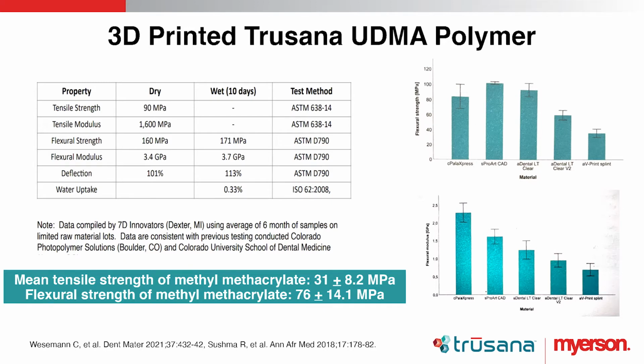When you compare Trusana, as far as the flexural strength and also the modulus, to, say, methyl methacrylate, the flexural strength is double, okay? And the modulus is 3 times, okay? So that's impressive. And then when you compare it to other polymers, there was a study by Wesseman, which is fascinating because he took a conventional material, a couple of the subtractive CAD/CAM materials, and then additive materials, and compared them to each other. And Trusana exceeded every one of those. So now we're at a point where we want to do some clinical trials.